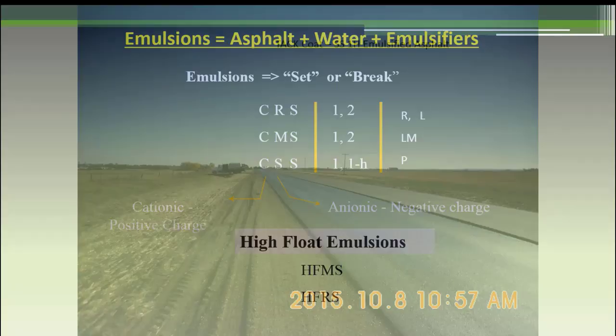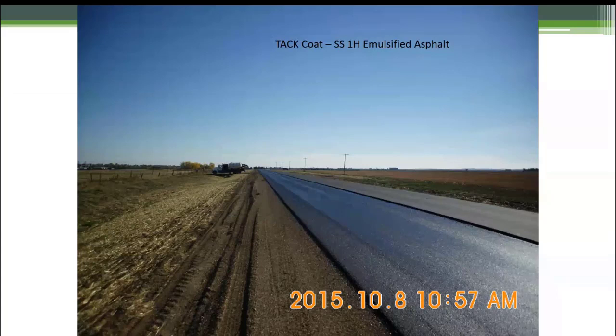There's just a picture of a tack coat. And this is outside of Mott, North Dakota, kind of south central, southwest North Dakota. And, really good shot rate, real good even distribution. And this was first shot, and I tried to look for my pictures of the distributor going as well. But, it turns from brown to black. The cure test is for a tack coat, it's got to weld the 2 layers. So you need the residual asphalt on the road. And that's why I wear my old boots when I'm out on jobs like this, is because I step in it. If I don't get some crawling asphalt up the soles of those boots, there ain't enough tack there.